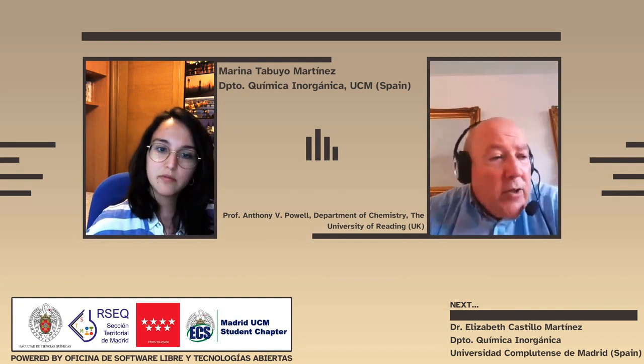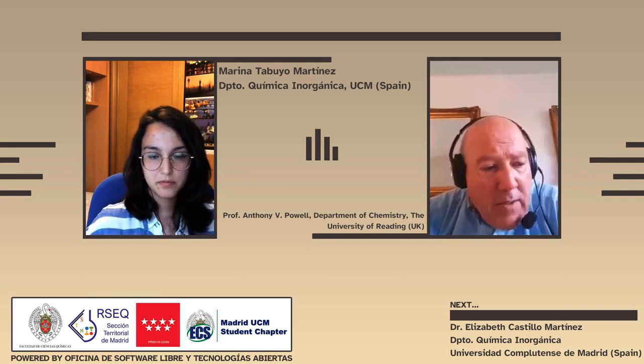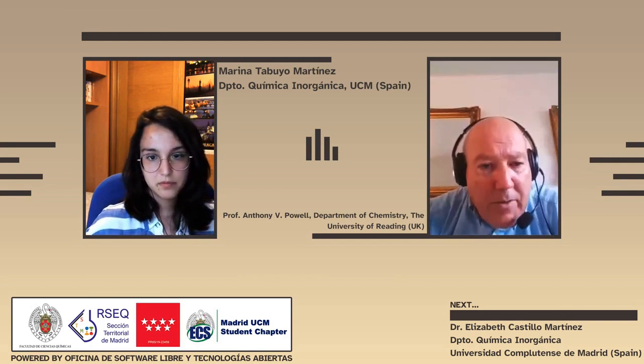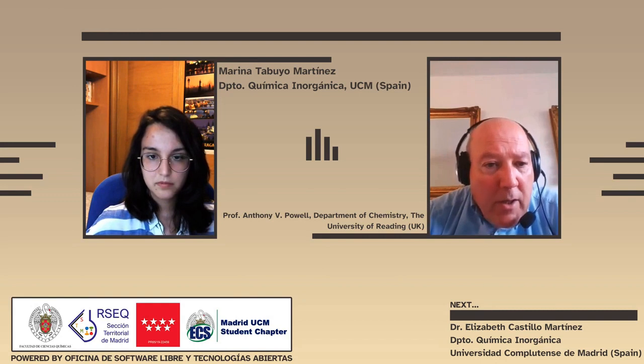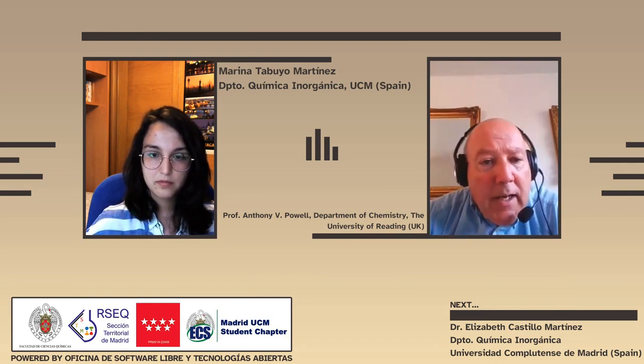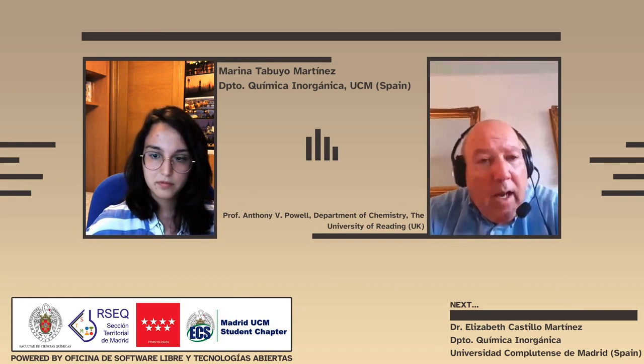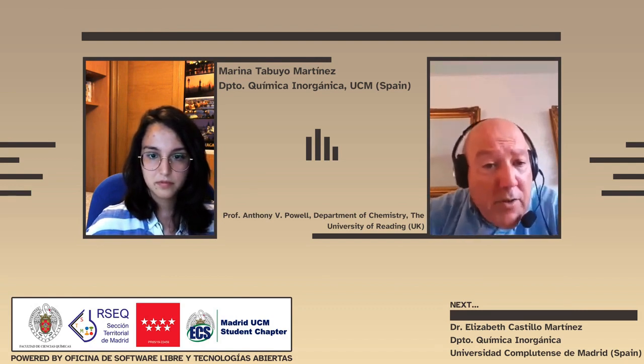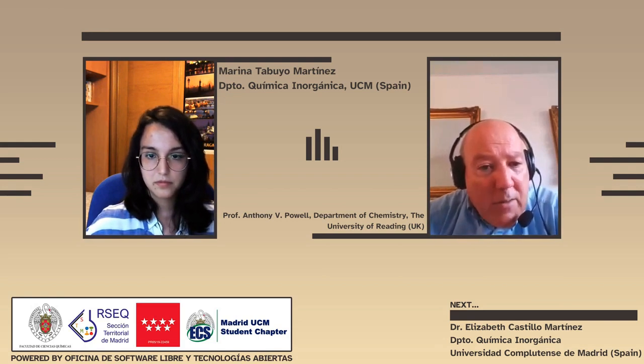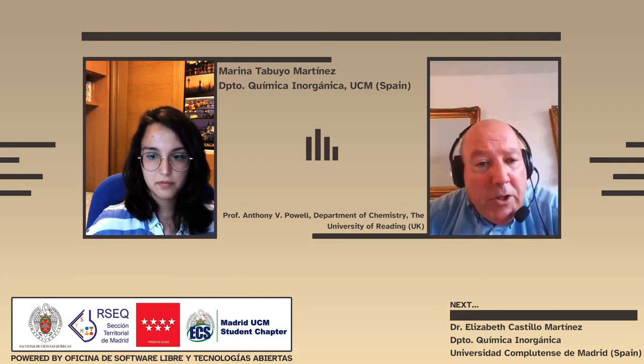Yes, we do. I didn't show it in the interest of time, but as well as those individual Raman spectra that I showed, we've also done Raman mapping of the surface of the composite. So we make the composite, we press a pellet, we then map the surface with Raman spectroscopy, which shows up the different carbonaceous regions, and those regions are actually very evenly distributed. I think it's because we're going down to that colloidal level when we do the mixing that we can get good homogeneous mixing there.